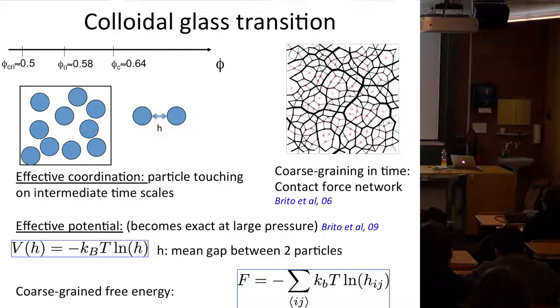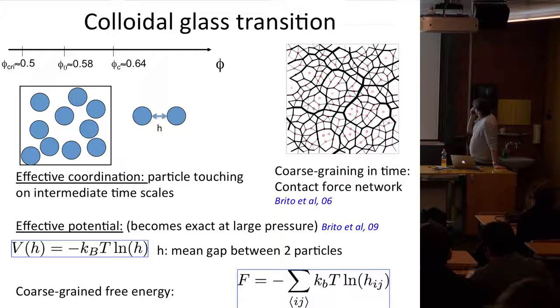One thing you can look at numerically is that they rattle around, so they actually exchange momentum with each other. And so you can define a force between two particles that are close to an average force: the total momentum divided by time gives you an average force. So if you average, you get something like that. So that's a 2D glassy system of disks. You have disks, they were rattling around those red positions. And you measure the force that they exchange. And what you find is that the contact force network looks very similar to contact forces in packings of athermal soft particles above jamming. Okay?